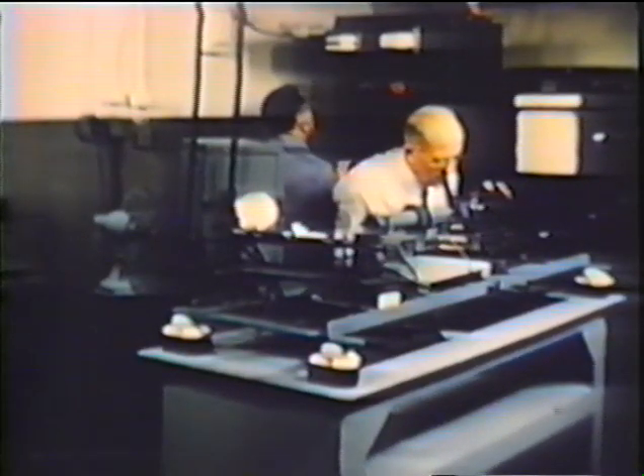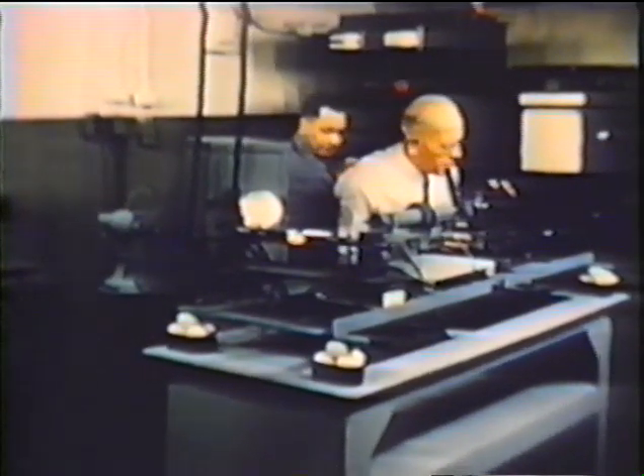With the miniature carbon rod test furnace in place for horizontal observation, the power is turned on. First, the mullite needle in the center, and then the alumina at the left melt in their proper order. The silicon carbide still stands, though we reach a temperature of over 4,000 degrees Fahrenheit. Now we are photographing our experiments at normal speed, so we observe them at their true elapsed time rate.